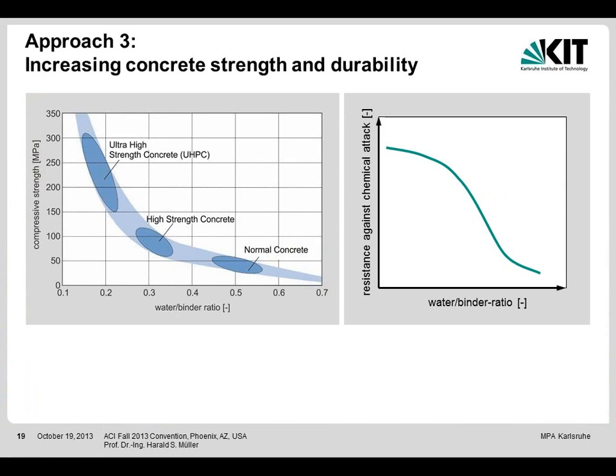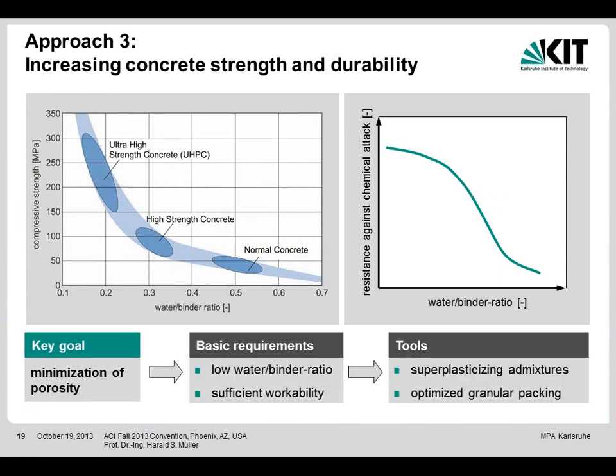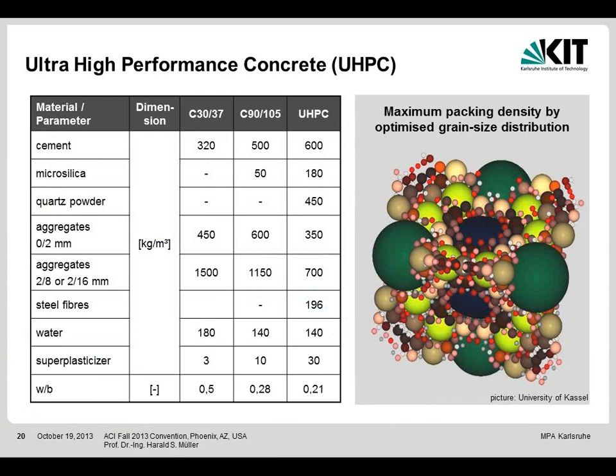At the same time, when reducing the water binder ratio, we have an increase of the resistance against chemical attack and other attack, and the key goal behind is the minimization of the porosity, and the basic requirements means a low water binder ratio, but at the same time we need a sufficient workability, and then we must use superplasticizer admixtures, and we must develop and optimize granular packing. There is much potential in this, but I don't go into details. I look to the other part. I look now to what may be done if we go to very high strength concrete, ultra high strength concrete.